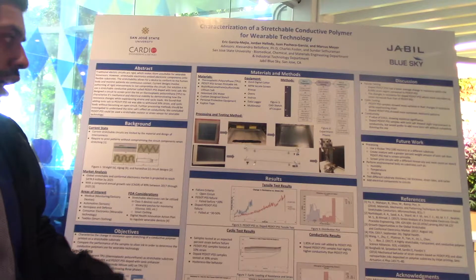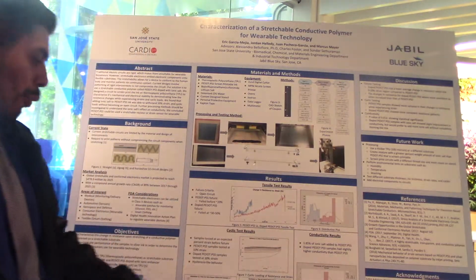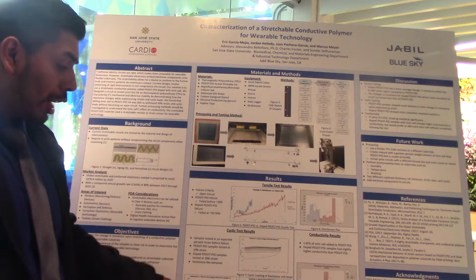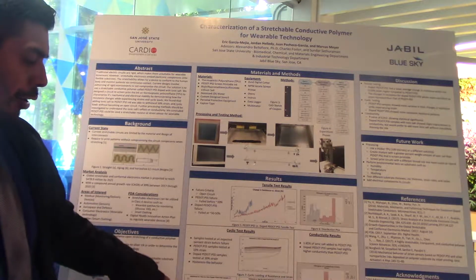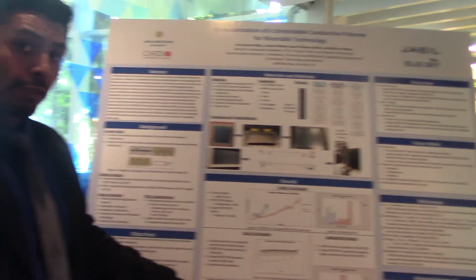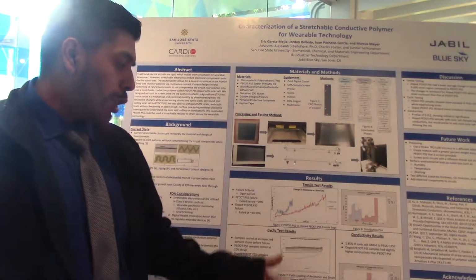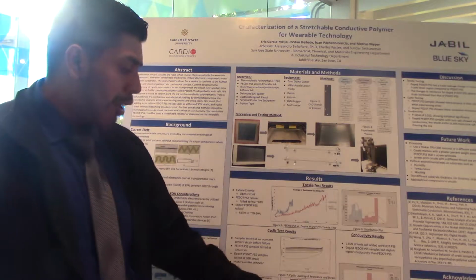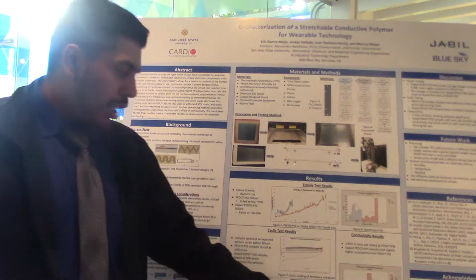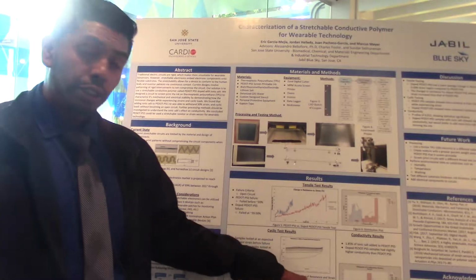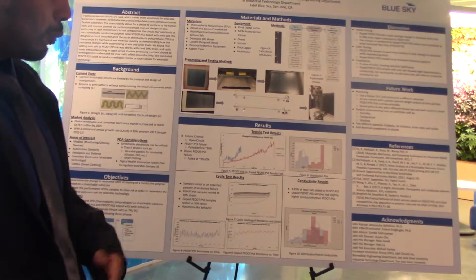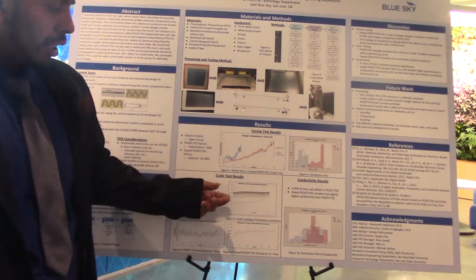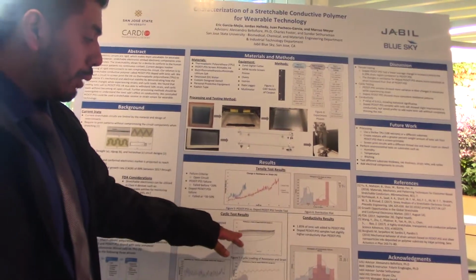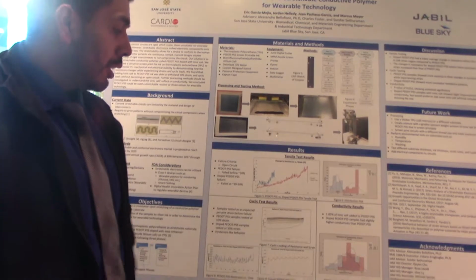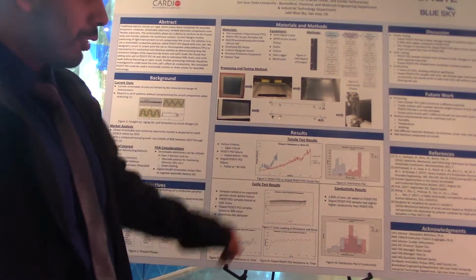As for the cyclic testing, this is one for PEDOT:PSS, and it shows how unstable it is. You can't really tell that we did it through 10 cycles. And when you look at the doped PEDOT:PSS, you can clearly see the different cycles that it was loaded and unloaded. We also plotted a resistance versus strain similar to a hysteresis loop. And we do see a jump in the beginning of the first cycle, but then you see how it stabilizes after the first cycle. And it really stabilizes after 5 cycles.